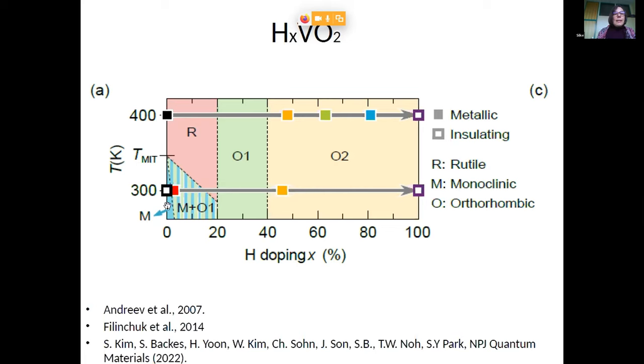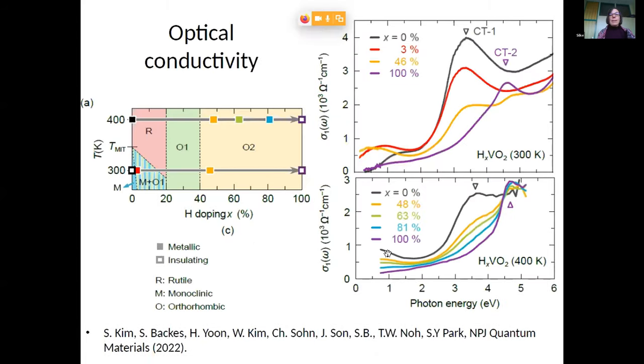If you do so, you see that the initial metal insulator transition, so here the insulating M1 phase, the metallic rutile phase, is actually somehow destroyed. The material gets metallic at dopings as low as 3%. It continues all the way here in a relatively bad metallic regime. And then at x equal 1, when you have 1 hydrogen per vanadium, you get back to an insulating state. If you start from the metallic rutile phase here, you dope and you get a worse metal, and eventually, again, you get insulating. So this has been investigated experimentally.